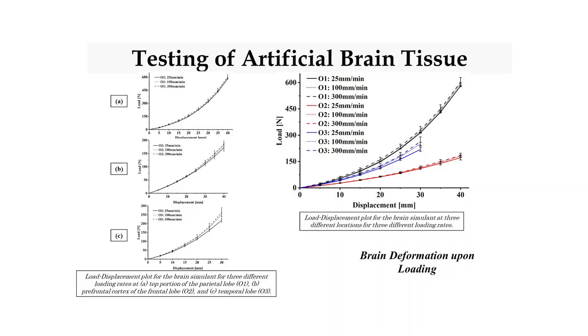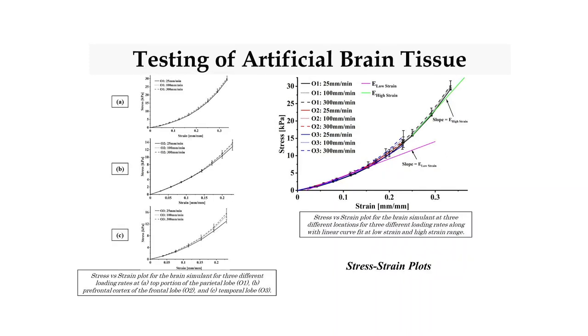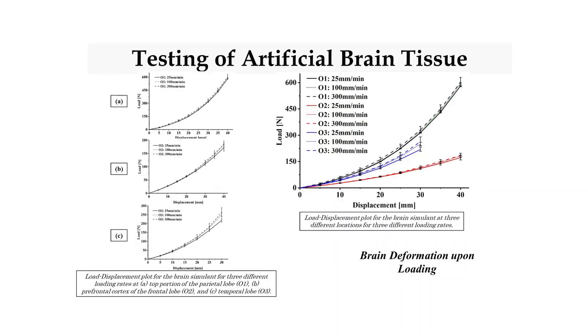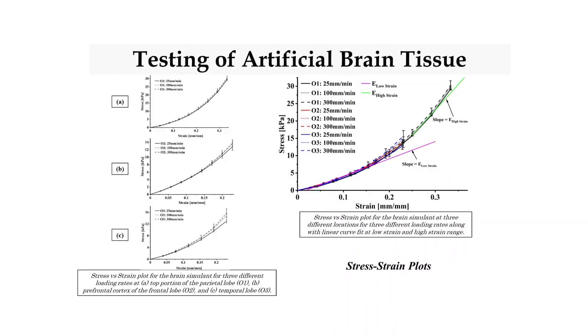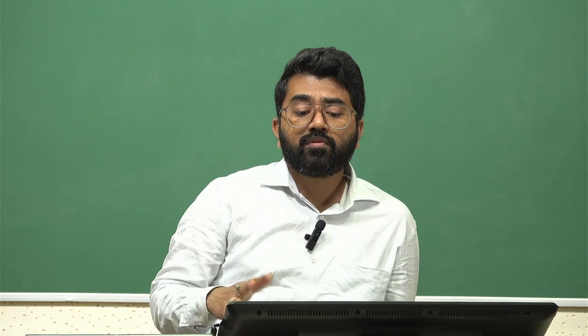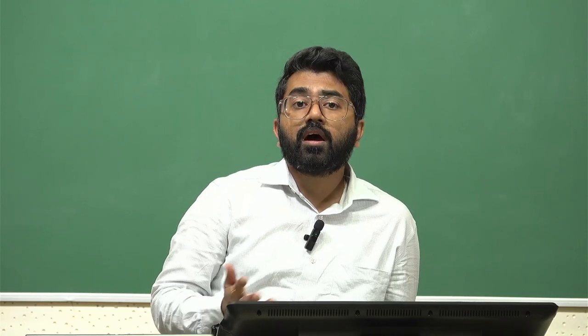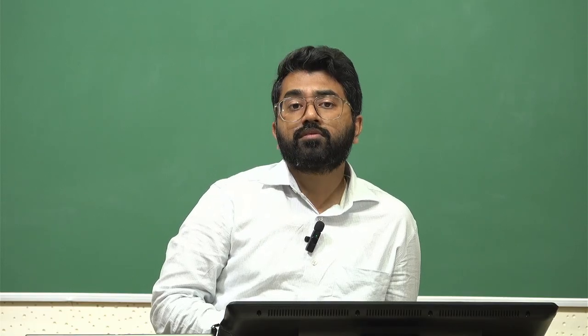I will just get to the key highlights here. What we did find out was, due to the orientation change, there was a huge difference in the mechanical property which was reported, but with the strain rate the brain tissue did not see a huge change in the mechanical property, right? We also were able to curve fit everything. When we went from load versus displacement to stress versus strain, almost those differences also vanished. We saw a very unique, almost single property of the brain tissue irrespective of the direction in which we placed it, irrespective of the strain rates, right?